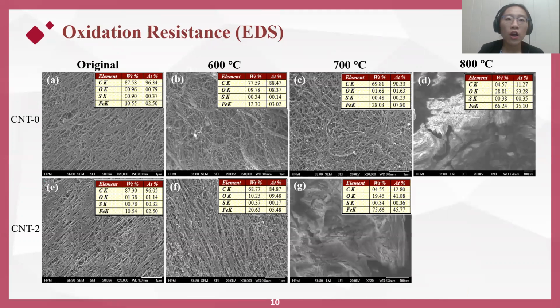For the as-synthesized samples, the EDS results indicate a similar catalyst residue starting point, with iron content at 10.55 and 10.54%, presumably due to the identical synthesis conditions, except for the water concentration. At 600 Celsius, which is about 550 Celsius on the sample, the relative iron content of the CNT2 group increased to over 20%, suggesting the initiation of carbon oxidation, which corresponded with the first derivative weight peak in the TGA curve. And the control group remained relatively constant.